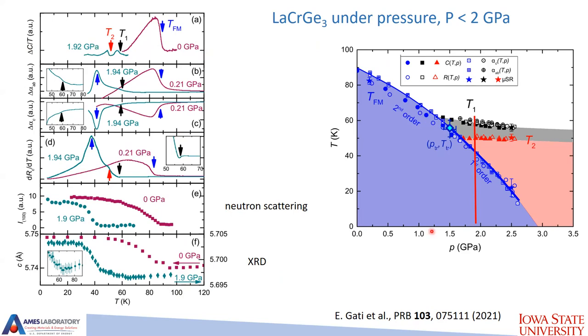At 1.9 GPa, which is somewhere here, specific heat gives you two transitions. Thermal expansion, but in specific heat, you basically don't see the ferromagnetic transition. In thermal expansion, you clearly see ferromagnetism and T1 in both orientations. In resistivity, you can see, probably, if you want to find them, both T1 and T2, as well as the ferromagnetic transition. In neutron scattering, you clearly see ferromagnetism, nothing else.